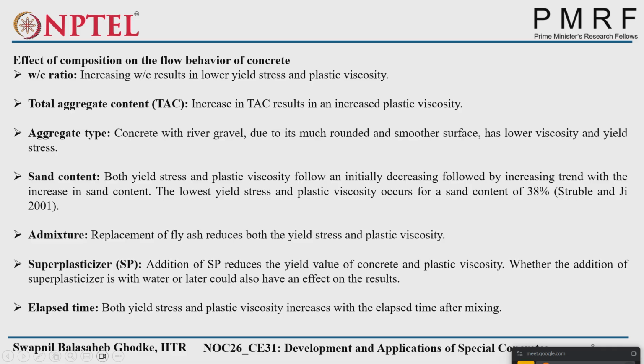Now, this sentence is totally subjective, because it depends on the type of sand you are using, whether it is 38% or more or less. This observation, according to this paper, is for the sand they used for that purpose only; they observed 38%. But if you are using different types of sand, with different gradations, your value may vary, and the yield stress and plastic viscosity results will also vary.